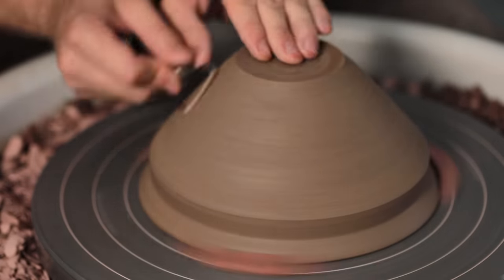Surprisingly, the glaze isn't as thick as I imagined, which is what I thought might cause it to split like this. But really, I think it's an issue caused by only glazing the inside, as snowflake crackle glazes like this are notorious for shrinking a lot and contracting more than the stoneware body underneath it. And I think in this case, that literally tore the pot in half.